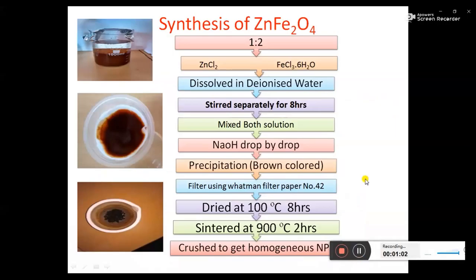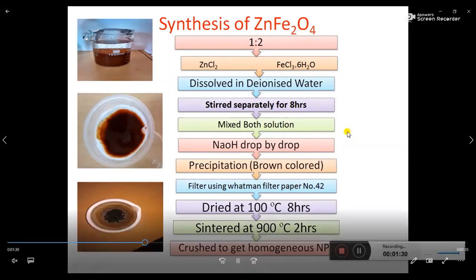Synthesis of zinc ferrite nanoparticles. A 1:2 ratio of zinc chloride and ferric chloride were dissolved in deionized water and stirred separately for 8 hours, then both solutions were mixed and the reducing agent NaOH was added drop by drop to the metal ion solution. We get a brown precipitate, then it is filtered by Whatman filter paper number 42, and the precipitate is dried at 100 degrees Celsius for 8 hours and sintered at 900 degrees Celsius for 2 hours. These are the photographs taken during the synthesis of zinc ferrite nanoparticles.